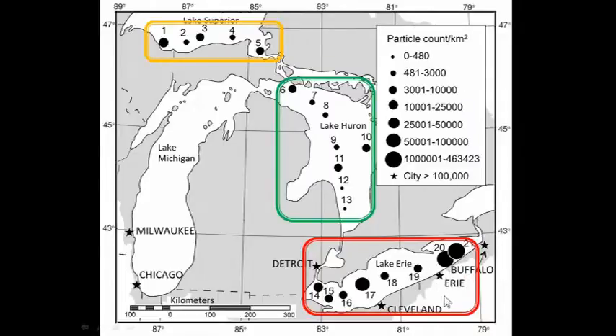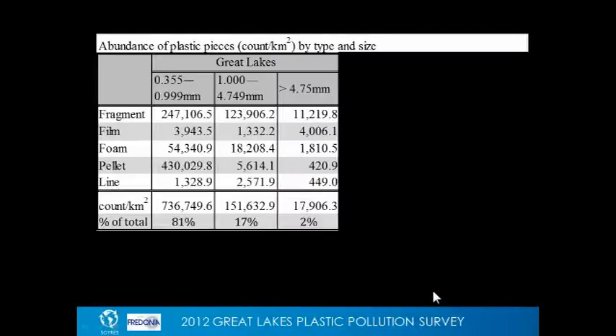So we want to talk about this in a little bit more detail. Here I'm showing a table of our data. When we're analyzing our plastics, we separate them into size classifications. Remember, our net is 333, so it would be 0.333 millimeters. So we have a size classification that goes up to 1 millimeter, another that goes from 1 up to 4.75 millimeters, and then a size classification that's bigger than 4.75 millimeters. Typically, this last column would be considered your macroplastics, and these other 2 columns would be considered your microplastics.